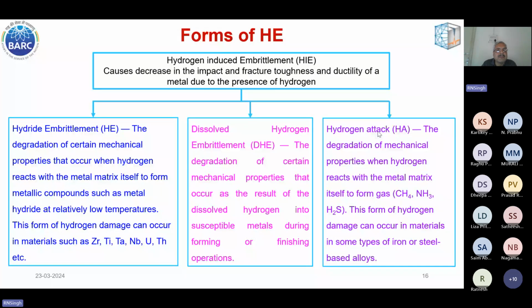Hydride embrittlement is exhibited by metals like zirconium, titanium, tantalum, niobium, uranium, thorium, etc. And common steels show dissolved hydrogen embrittlement. And hydrogen attack, as I said, occurs in some types of iron and steel based materials during operation in power and process industry at a temperature of about 500 degrees Celsius. So they exhibit this kind of failure.